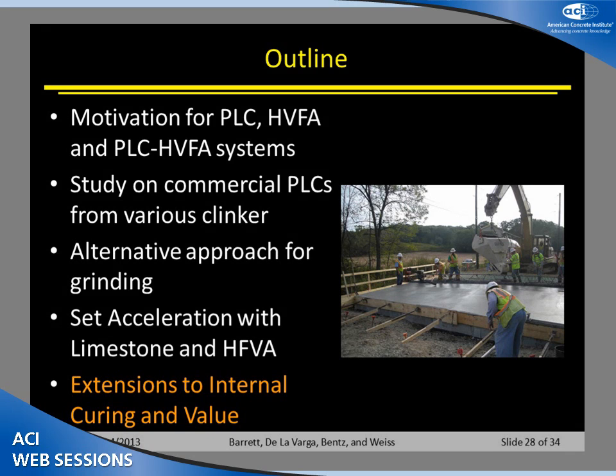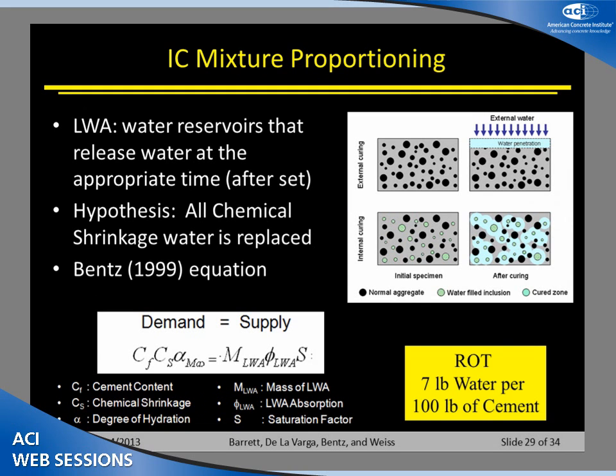So this is a particular deck. Now this is not a high volume fly ash deck, but this is a particular deck with internal curing. And if you haven't seen internal curing before, and this may sound like a different type of topic, conventionally we have concrete up here, and I would hope, as I mentioned earlier on, that we would be minimizing the paste content. So I hope you have a little bit more aggregate than what I've shown here, these dark aggregates in the system. But the basic idea is we do external curing in a lot of our applications.